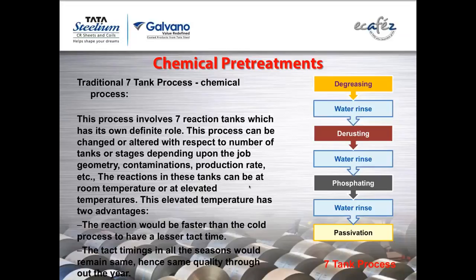reactions. Then you have derusting, where we are removing a lot of oxidation. This is different from pickling. Pickling will have a very high concentration of acids. Derusting does not have that high a concentration of acids. It will only react with the surface or flash rusts, which are created especially in monsoon seasons, especially where you are doing some grinding work after welding. These areas you will find a little bit more rusted. This rust can be taken care of.